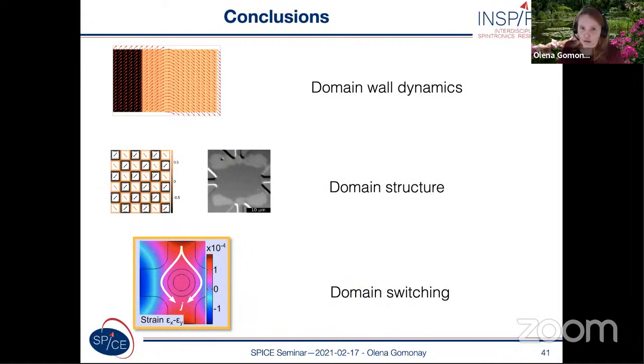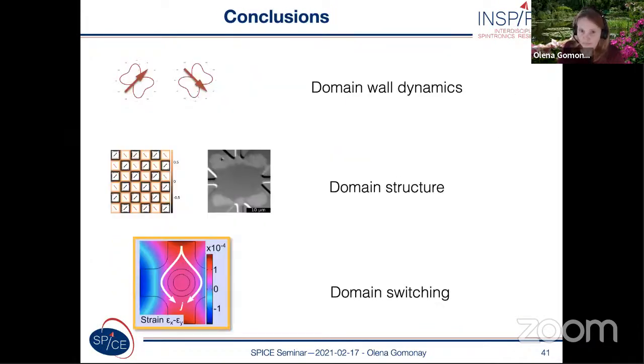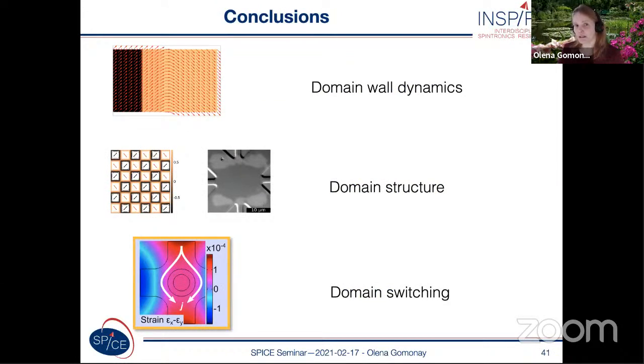So I'm at the end of my talk now. Oh, sorry, I would like to make conclusions. We considered the dynamics of the domain wall related to magnetoelastic interactions. We found that strains could be extremely important and change significantly the magnon spectrum and the dynamics of the domain walls. The strains can affect the domain structure and can be responsible for the formation of the domain structure, and strain is also very important for switching and for application in real devices.